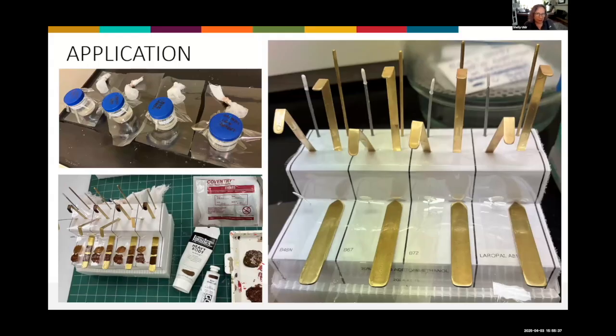So I applied each mixture to clean test brass. Each set had one 3/32 or 2.4 millimeter rod, which I fully dipped once, then waited a minute and then dipped the top little bit, 1/2 inch or 2 centimeters, in a second time. I wanted to see the difference of thickness of the material. Then there was a bent strap that was just dipped once in the solution.